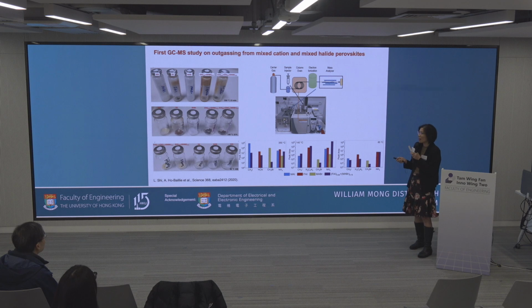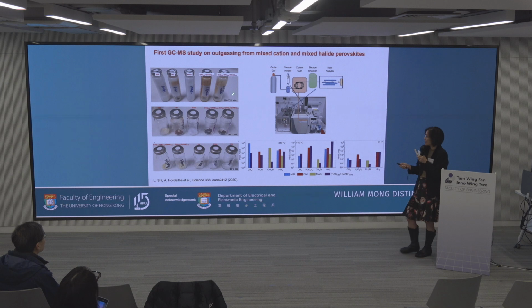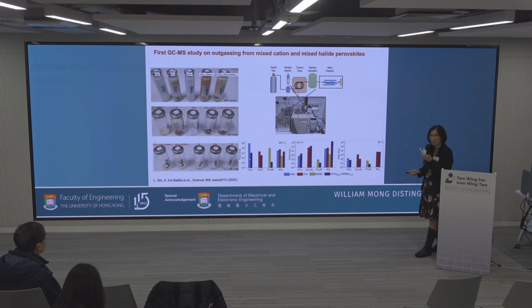So even back then, Mercouri was looking at mixing the lead and the tin, and there are also people mixing the halide, the iodine and the bromide, into the perovskites. So we want to find out why the mixed ones are more stable and what happens if you mix the wrong species. What we did was use mass spectroscopy to identify the signature decomposition or outgassing products from the precursors. So we have the MAI, FAI, MABr, and then we also have the mixed perovskite precursors. We heat them at 85, 140 and 350 degrees, and then we look at the outgassing of those signature products from each.